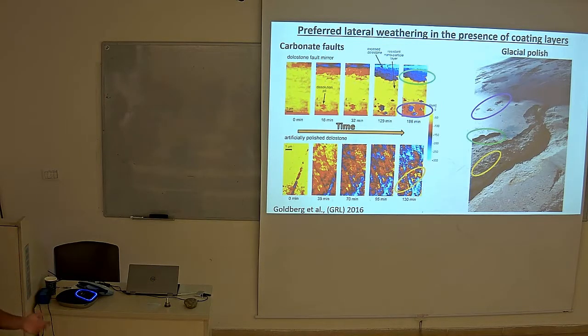And what we see, this is with time, is that the initial smooth surfaces are becoming something like karst weathering in the Z direction, and differently for the naturally polished one, we start to get weathering pits that actually evolve laterally. And we also get a sharp margin, very similar to what we see in glacial polish. And if the glacial polish scales off, we can get similar structures like in the irregular polish.